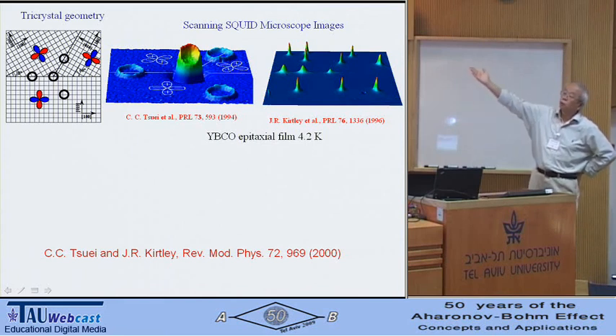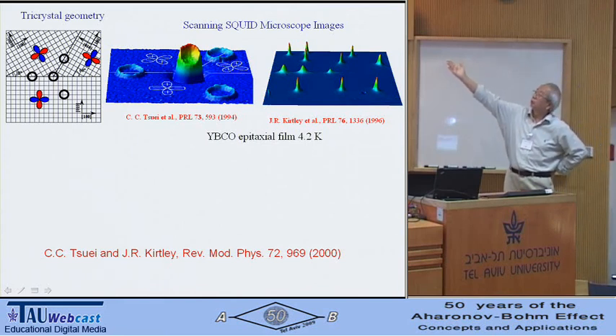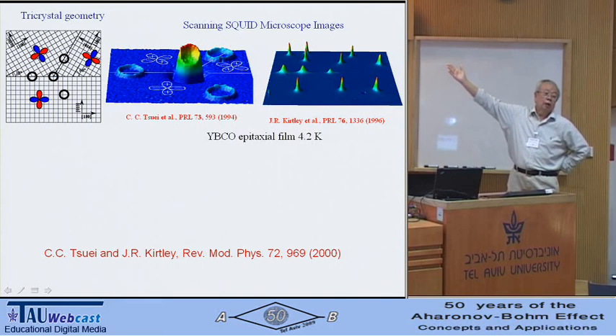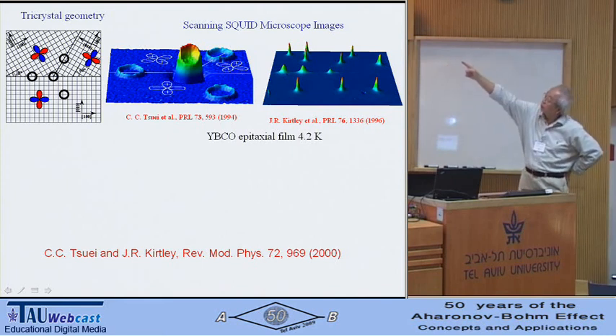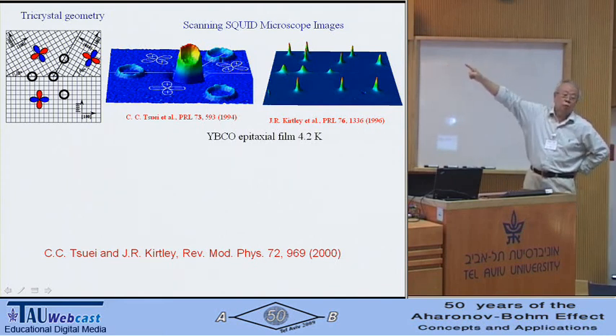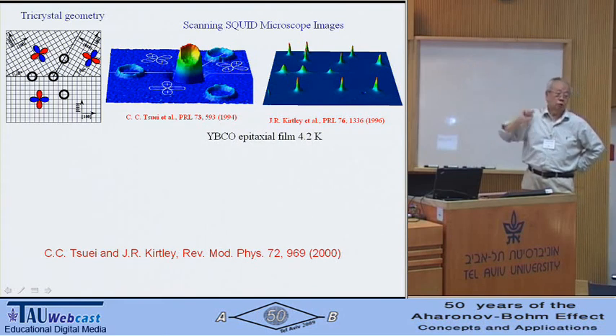And using a scanning SQUID microscope, look at the vortices. And you see at the center, there's a small vortex in there. That's a half-flux quantum at the tricrystal. That's where it's supposed to be, if it's a D wave.